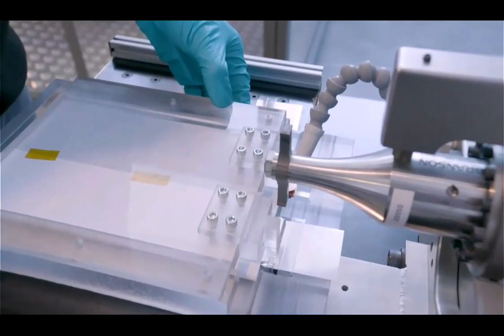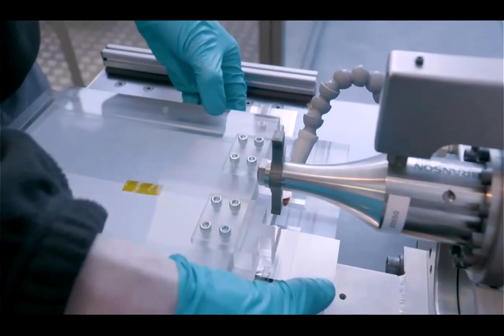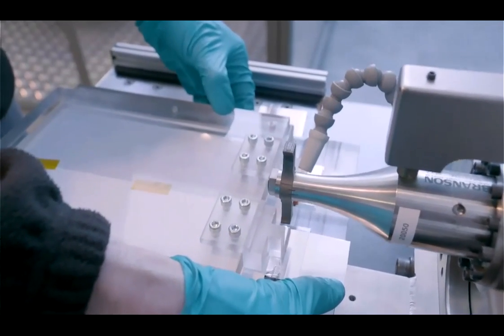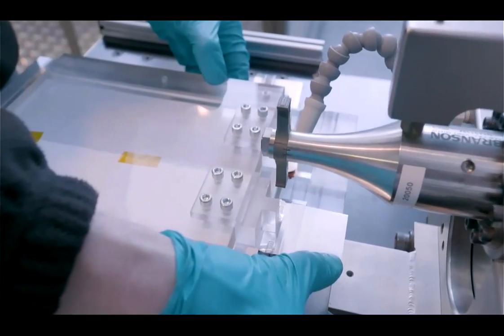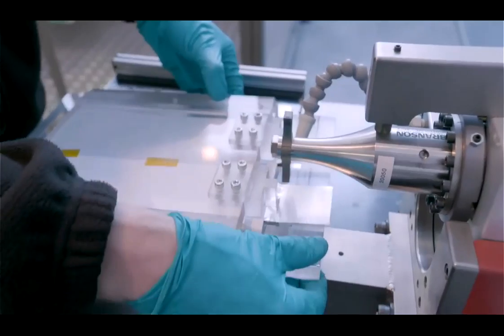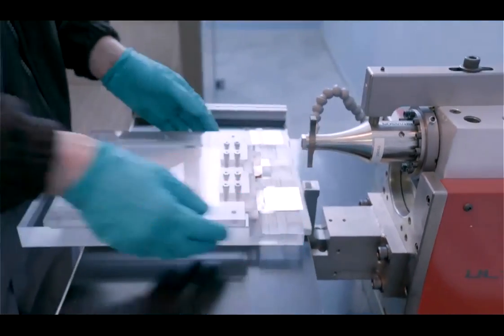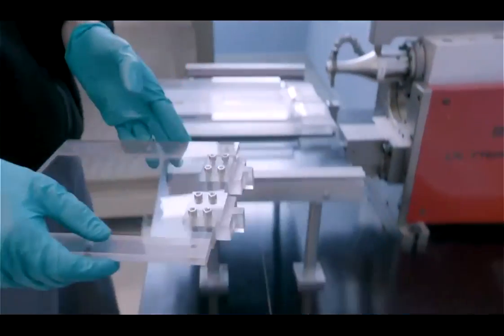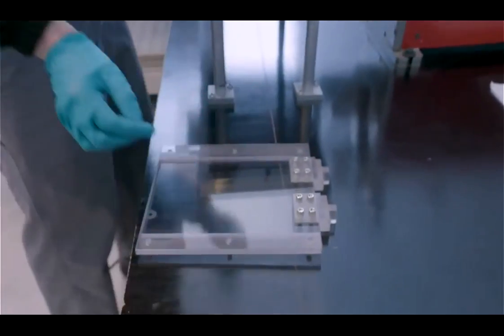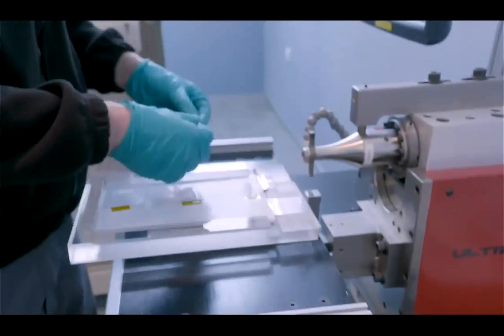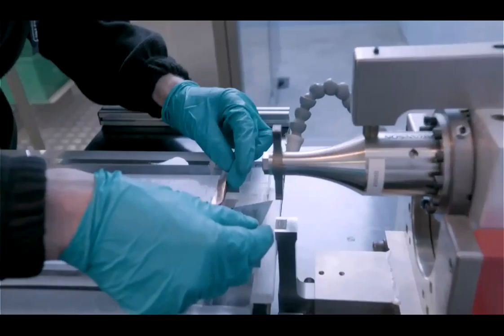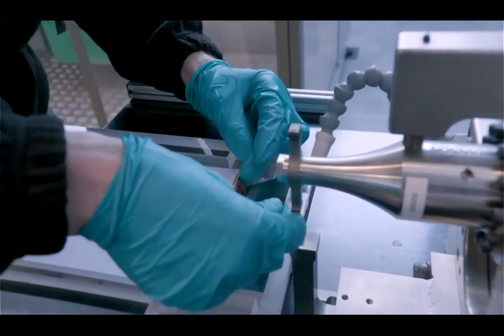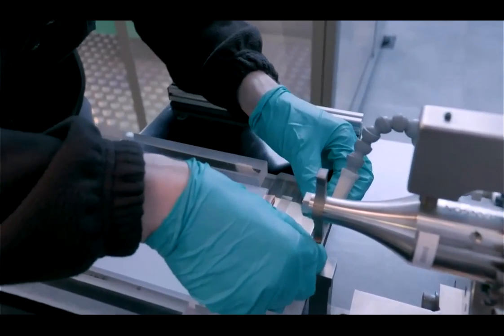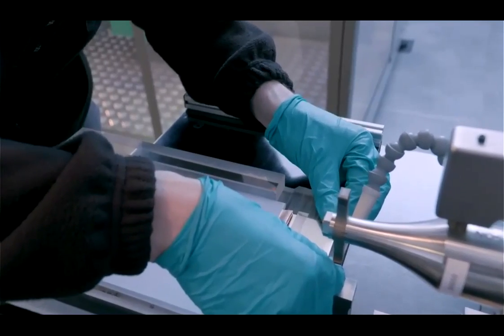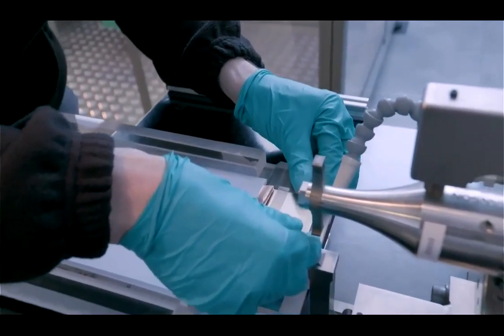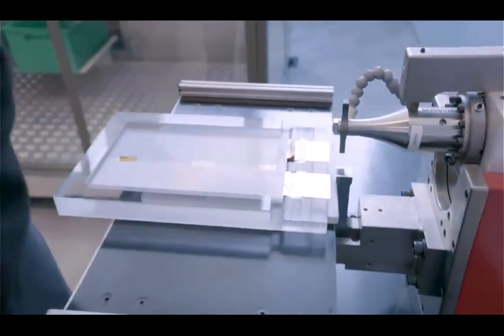So the time and the energy have to be adjusted for the anode, for the cathode, and it will depend also on the number of electrodes that we have. In our stacking machine, we can stack up to 50 sheets of electrodes to get a cell capacity of 30-40 ampere hours, something like that.